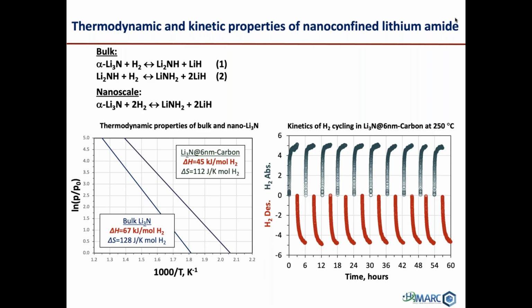And interestingly, we find that this material is very stable. We can cycle it at 250 degrees C. In other words, you heat it up, it releases hydrogen, then you repressurize it. In this case, it's about 100 bar, and you can regenerate it. So this is a cyclable, renewable material for storing hydrogen. And an important point here is that you're storing it not only in a bulk form, but at pressures a factor of 7 lower than you would have to use if you were using pure pressurized gas. And that's a big deal because the compressors and infrastructure required to build a fueling station for 700 bar is substantial. It's quite expensive.